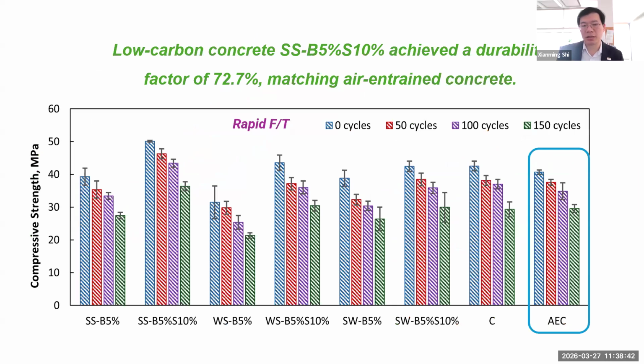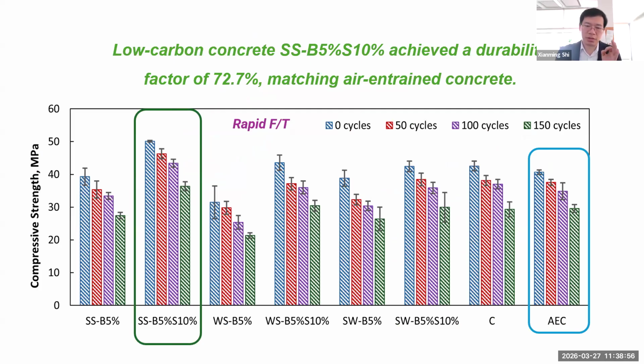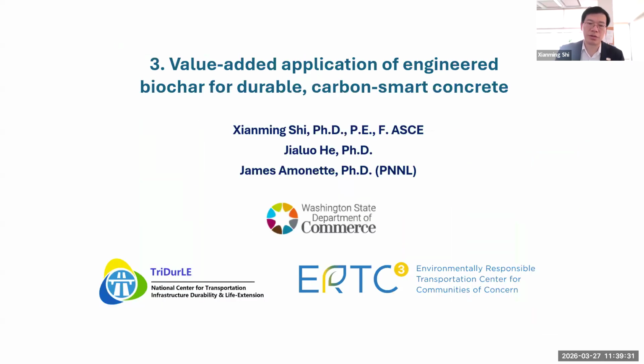But if we balance all of that and we subject the concrete to rapid freeze-thaw testing, after even 150 cycles, you can see the air-entrained concrete versus this 5% cement replacement, 10% sand replacement, we're achieving comparable or actually better strength or residual strength because the initial strength was high, so your residual strength is still higher than the control. And when we calculate the durability factor, it is almost 73%, which matches with air-entrained concrete. So it's all very good. In other words, we don't actually need an entrainment for biochar amended concrete to be used in freeze-thaw environments.